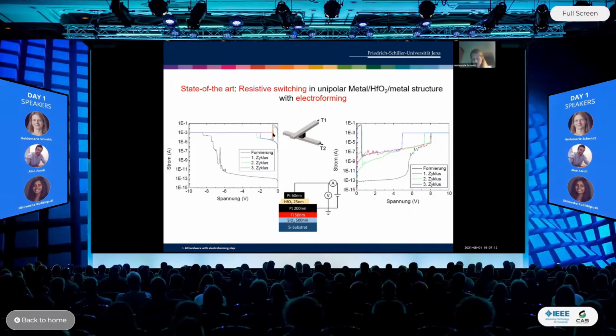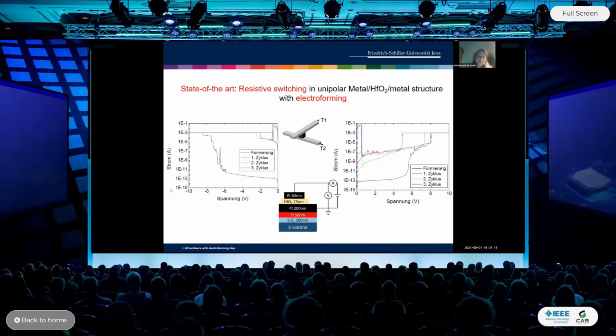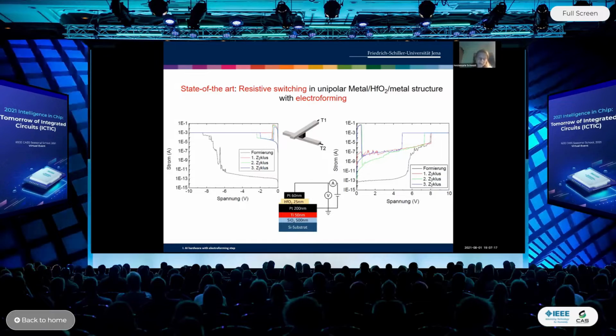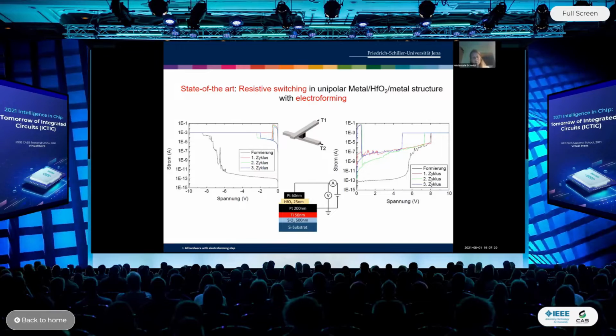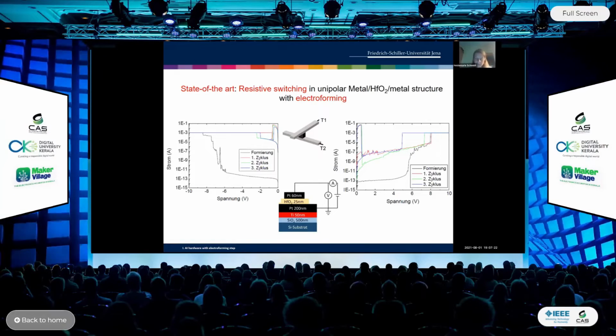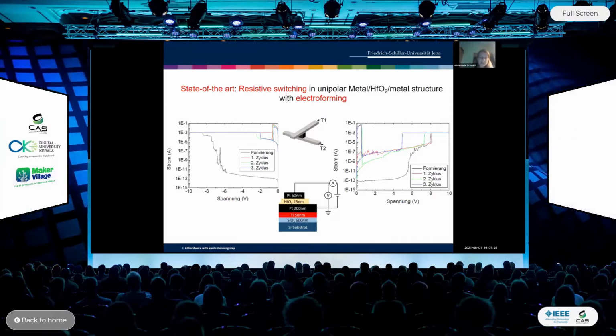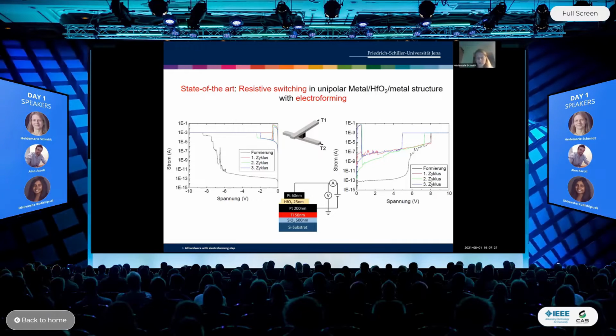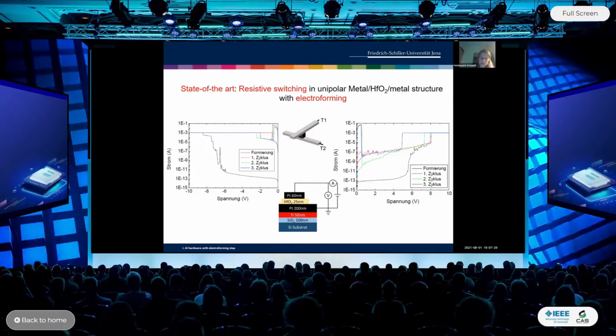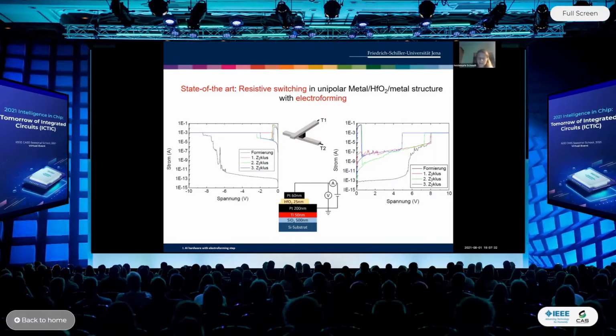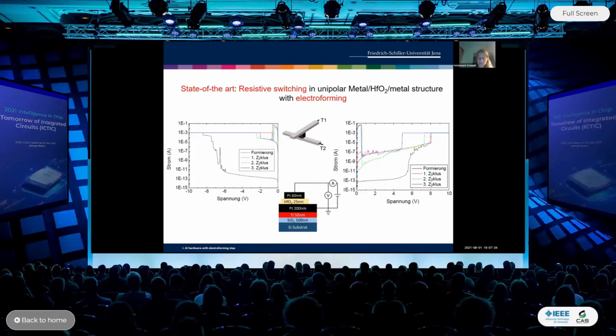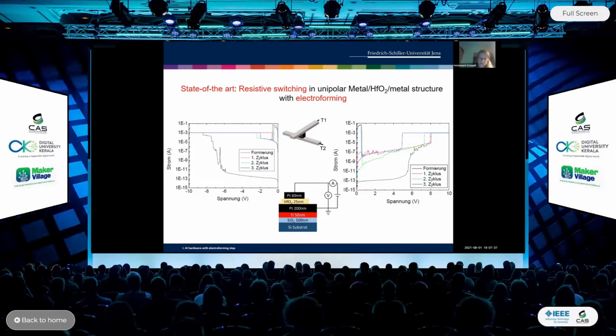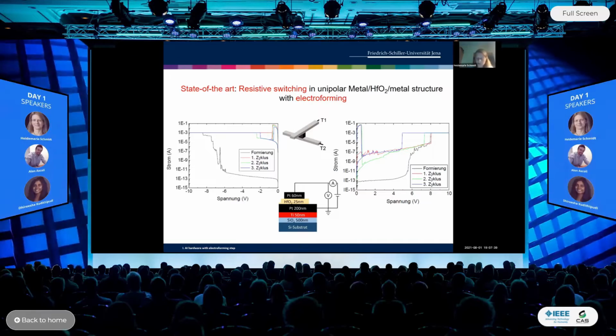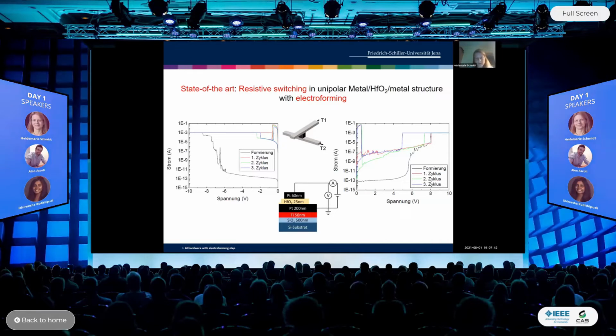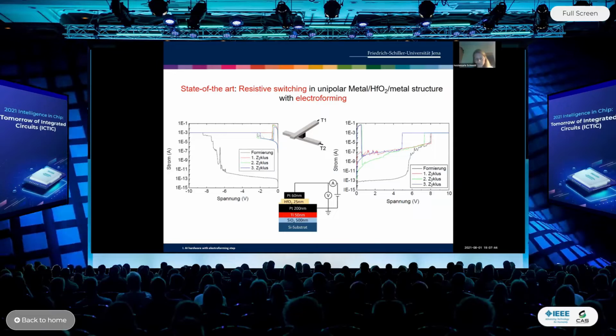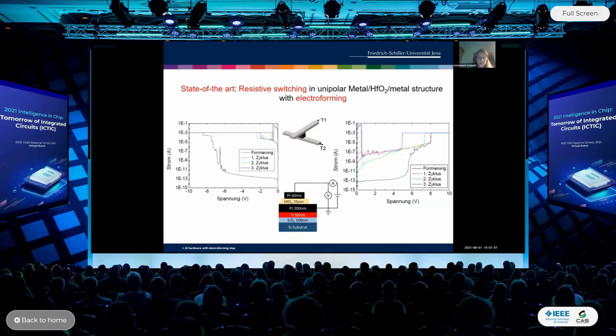This property, that you need an electroforming step with a large bias to bring this memristor into functionality, is called electroforming. And it has several disadvantages if you go towards an array of memristors, where you have to address step by step all the memristors which are formed in this array and which have to work later on with the same small writing bias which we see after the electroforming step.